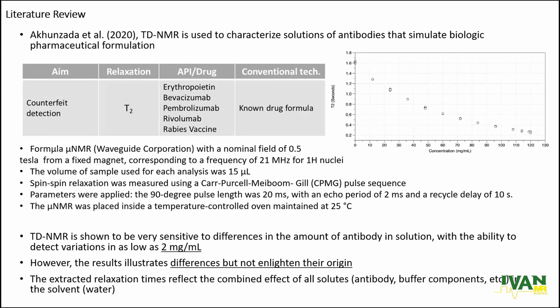science. In another study, they used TD-NMR for characterization of solutions of antibodies that simulate a biologic pharmaceutical formulation. These are the parameters, and TD-NMR is shown to be very sensitive to differences in the amount of antibody in solution, with the ability to detect variation as low as 2 milligram per milliliter. However, the results illustrate the difference but do not explain its origin. The extracted relaxation times reflect the combined effect of all solutes, because the solvent is water most of the time for biotechnological drugs.